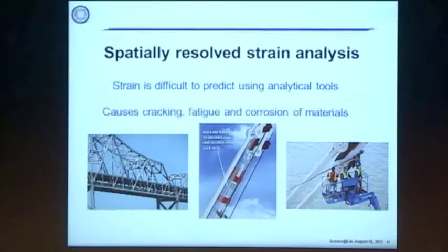Sorry, they don't move as fast as what? They do not move as fast as the speed of light. So thermal energy neutrons, by the time the pulse is produced, they reach our detector, it takes from microseconds to milliseconds. So if we can time tag every neutron, we can measure the energy of the neutron. And I'll tell you why we want to measure the energy of the neutrons which went through the sample. One of the applications is to measure strain in materials.